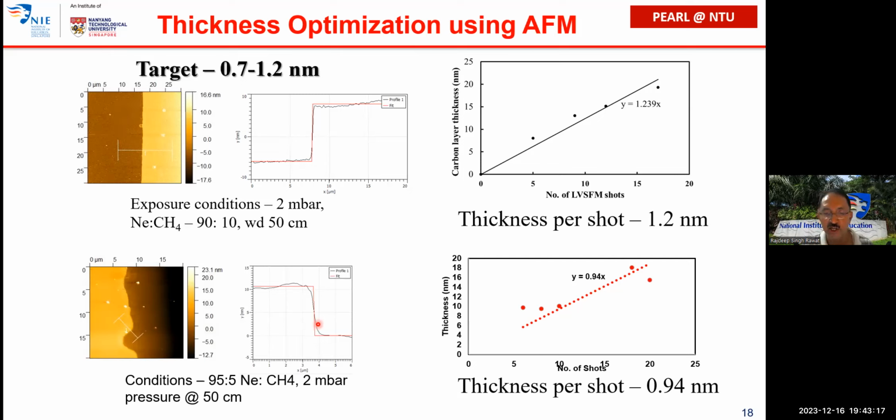This coating needed to be done on a magnetic material. If we operate our plasma focus in the fast focus mode, then the ions that are going to come out, if they are the ions of the filling gas, and in this case, we are going to have one of the precursors, the carbon gas. If the carbon plasma is too energetic, it is going to modify even the magnetic layer. And we did not want that. We did not want the magnetic layer to change its magnetic properties.